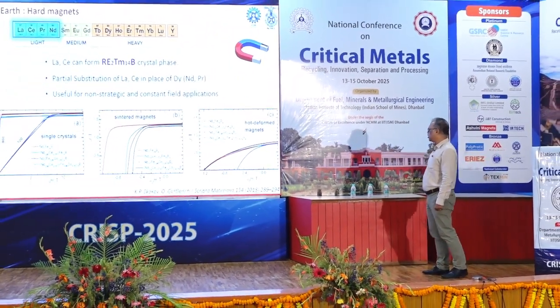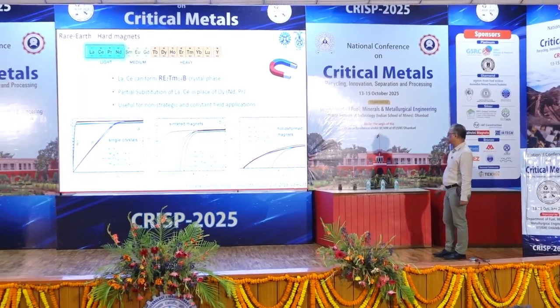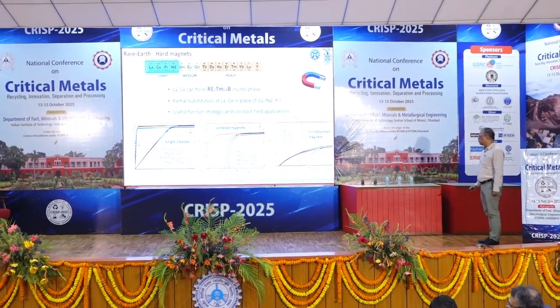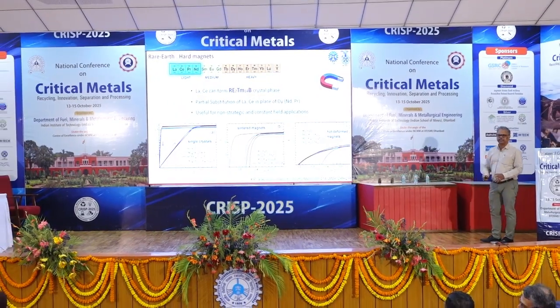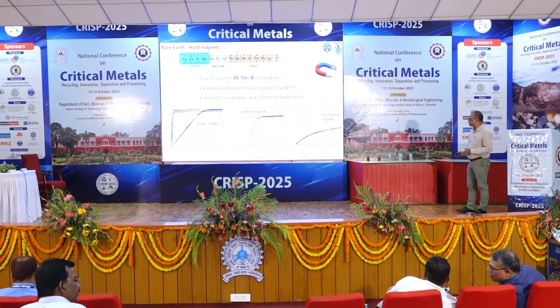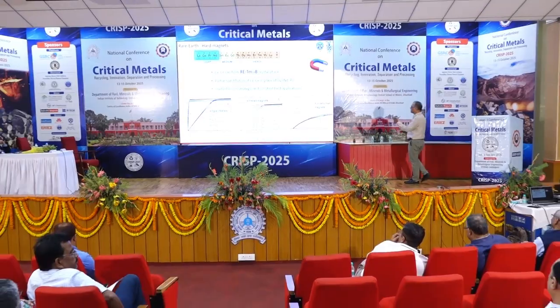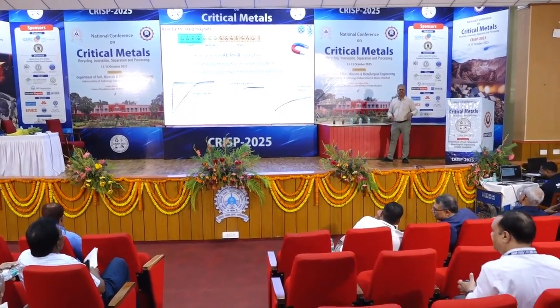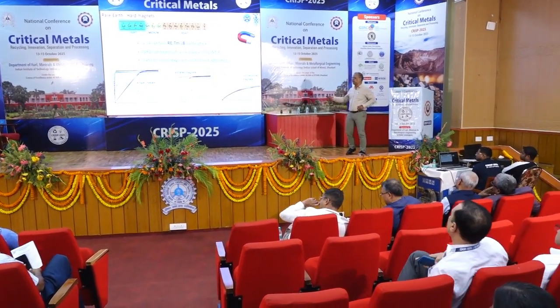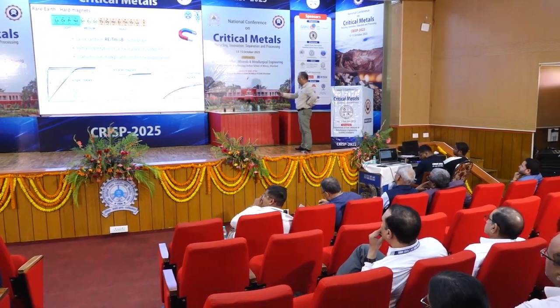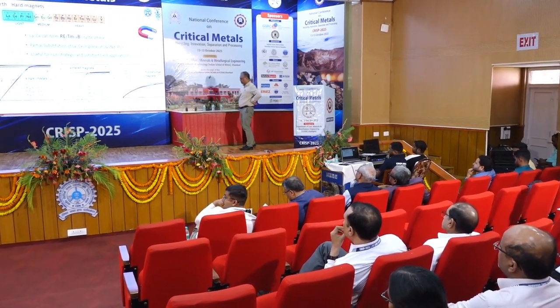But when you talk about the hot deformed magnets, when you have only cerium and cobalt, it is the blue color, which is a little bit different, but in the other cases it is alright. So if you have hot deformed magnets with neodymium replaced by cerium and cobalt, you can go up to a certain level by this processing route. Of course, this is not our work, this is taken from this particular paper.